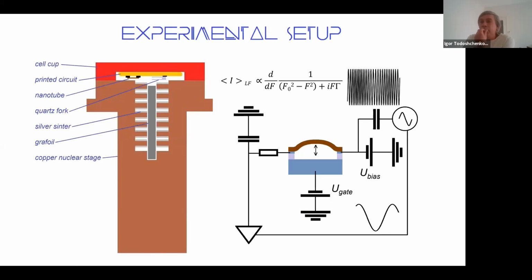So, the experimental setup. We have a sample cell inside the copper nuclear stage. We have a sinter for good heat exchange between the copper coolant and the sample helium. We have a suspended nanotube, and we have a quartz tuning fork, because it also adsorbs helium, and we can somehow control what's going on with the nanotube.